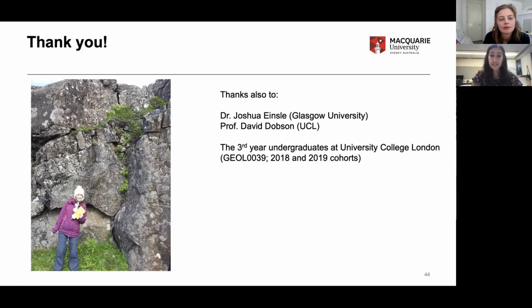The other thing is EBSD is great. Minimum grain size, someone's already said, is only about a micron that you can achieve. And it comes at a very low throughput. It's almost 8 hours an EBSD map compared to the 3 minutes that we did here. But I think for people that do have complex textures, it's a great way to check if it's possible. But we wanted to make something that was fast and easy access for people who didn't necessarily have EBSD available.